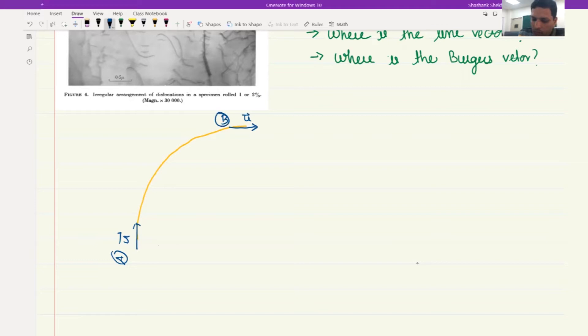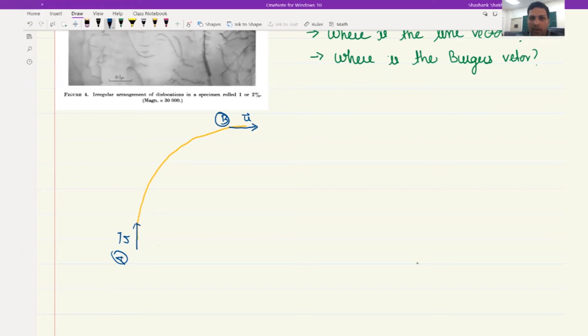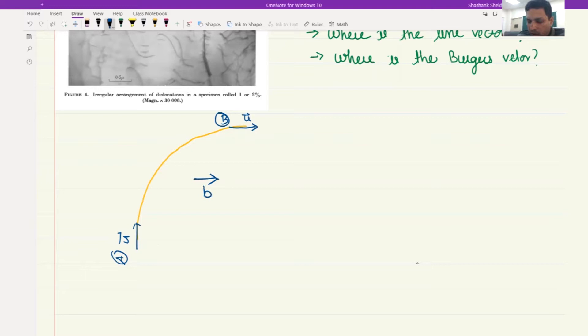Let's call one location point A and another point B. At point A the line vector is in one direction, and at point B it is in another direction. Now what about the Burgers vector? For one individual dislocation, the Burgers vector remains constant — it should not change with location on the dislocation. The Burgers vector is a slip vector; it defines the slip direction. The curvature of the dislocation does not change the direction of the slip vector, so the Burgers vector must remain constant.